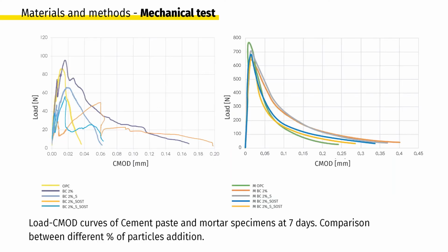From the curve obtained from the three-point bending test, the fragile behavior of pure cement and the influence generated by the presence of biochar in the mixture can be observed. In the case of mortar, the tendency is constant with respect to the cement-based specimens.